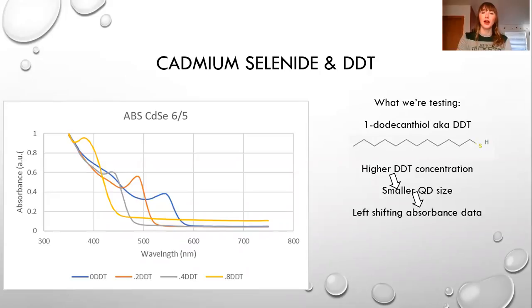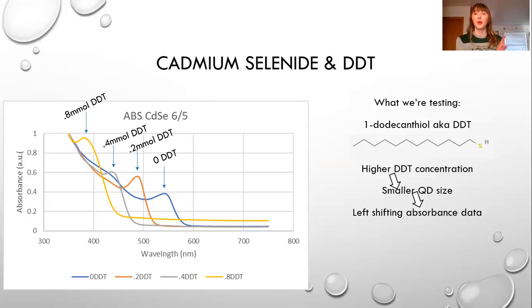But in this graph on the left, this was research I performed two summers ago in the lab, and you can see that depending on how much DDT we add, it changes the size and the photovoltaic properties of these quantum dots. So this is with no DDT added, which research on these quantum dots has been done before, and their efficiency in lab testing is about 11%, which is not ideal. But the more DDT we add, it shifts where these quantum dots absorb the light and energy that hits them. So with a higher DDT concentration, we make the quantum dots smaller, and we have a left shifting absorbance data as shown in this graph.